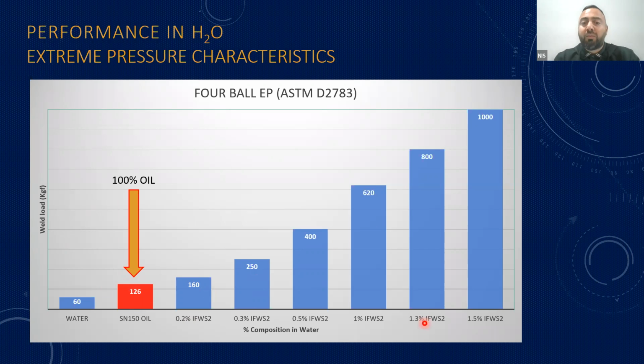So 98.7% of water and 1.3% of particle, you're getting to 800 kilogram force, which is basically the maximum of this ASTM standard test. So anything above 800 is called no weld. I can tell you that not many greases or heavy viscosity oils can get to this number. This is a very high number, and it's very remarkable as well. And we're talking about water.